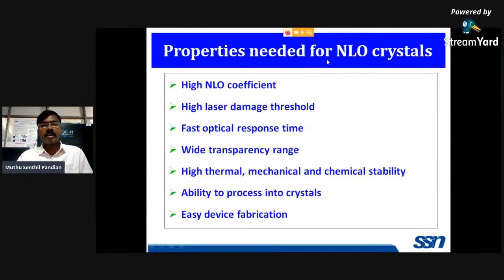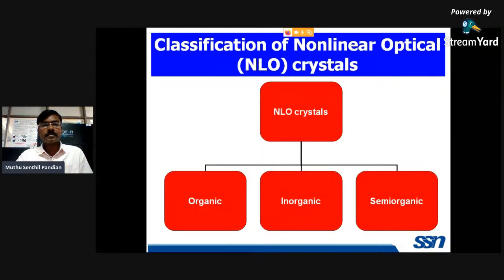What are the properties needed for nonlinear optical single crystals? It should have a high NLO coefficient, and for laser application one must know the laser damage threshold value, so the laser damage threshold of the grown crystal must be very high. It needs fast optical response time, a wide transmission range in the UV, visible, and near IR region, and high thermal, mechanical, and chemical stability. The ability to process the crystal and the device fabrication steps should be very easy, so when we go for practical device application, it is essential. The nonlinear optical single crystals can be classified into three categories: organic single crystals, inorganic, and a mixture of organic and inorganic, which is also called semi-organic material.